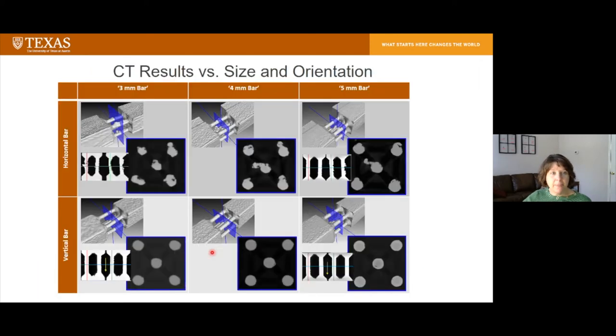And one of the things we found is that although we expected a 195 gigapascal elastic modulus, what we found was quite a bit lower, and that the horizontal struts were much worse than the vertical ones. So when we CT scanned some of our specimens, it became clear why that was.